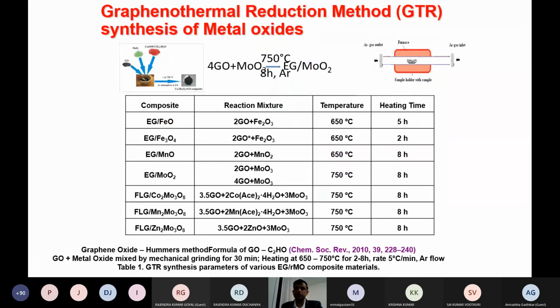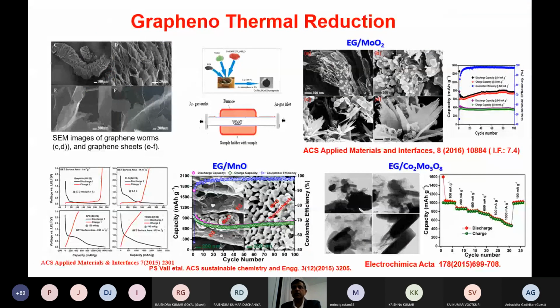At the end, the same materials we have also looked at for batteries. I'm not going to discuss too many details on this. Again, for example, instead of carbon, you can use graphene thermal reduction, meaning you can use RGO, exfoliated graphene. You put the material in at 650 degrees, depending on the oxide, and you can prepare a complex oxide. The advantage of this technique is that we can prepare reduced oxides as well as get a graphene coating. That is the beauty of this method, and we can get different types of oxides, from simple to complex compounds.